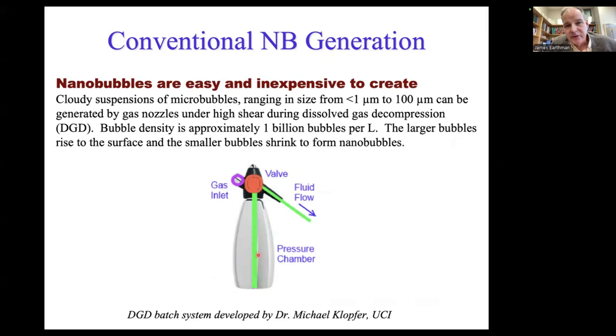There's other conventional nanobubble generation methods that were already out there. People were using. This is one that we have in my lab now. It's what I call dissolved gas decompression. You put water in a container. This is actually a modified seltzer bottle. You put gas pressure on top of that water. 100 psi is enough. And then you release the water out a small orifice and tube, and microbubbles are produced. The water comes out cloudy, and after the microbubbles shrink below a certain size, the water gets clear, and that's when you have nanobubbles.